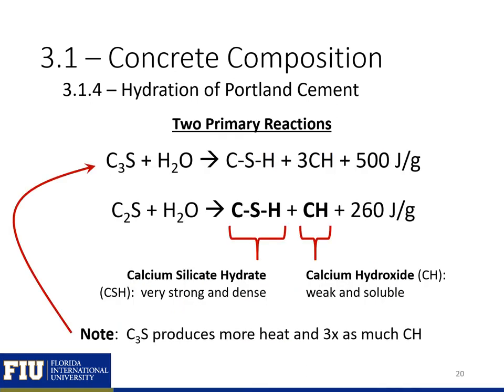There are two primary reactions that occur during the hydration of Portland cement. C3S and C2S both react with water to form CSH, CH, and heat. CSH is calcium silicate hydrate and is a very strong and dense hydration product. CH, or calcium hydroxide, is weak and soluble. Note that C3S produces three times as much CH as C2S. So although C3S causes a quicker initial strength gain, it leads to more CH, which weakens the concrete matrix.